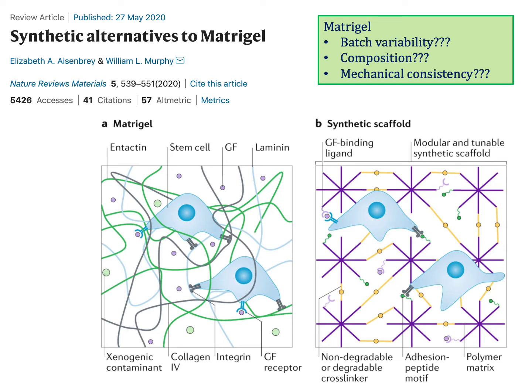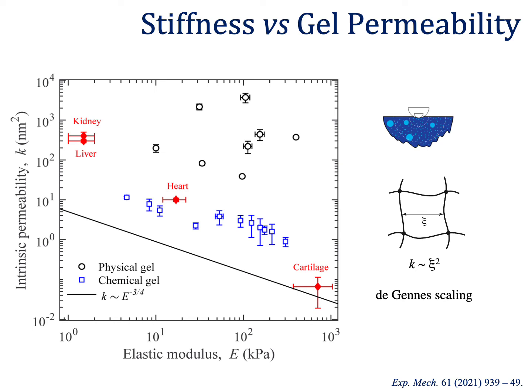The picture on the right is an example of a synthetic scaffold that is being used to study different types of cell differentiation and to address some of the issues that arise with Matrigel. It has significant batch variability, and that leads to variations in both its composition and also its mechanical properties, which from our view as bioengineers is a particular problem. However, one thing that the design of these types of scaffolds have to take into consideration is the mechanism of bonding within the hydrogel. So here we have a plot of elastic modulus versus the intrinsic permeability. The permeability is essentially a measure of the pore size within the hydrogel, and it relates to how easy it is for fluid to move through the hydrogel or artificial extracellular matrix.